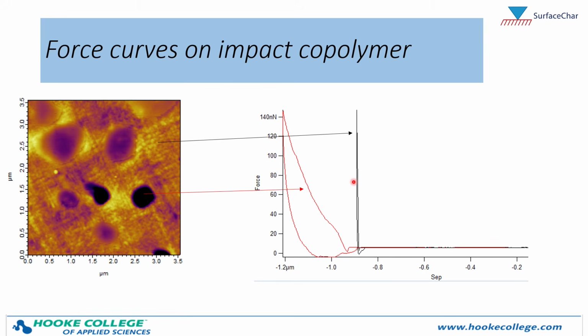So notice we have a pretty big adhesion gap here in the red curve on the rubber versus a much smaller adhesion on the thermoplastic, which makes a lot of sense. And finally, I'd like to point out the hysteresis between the approach and retract on the rubber, much bigger gap here than on the thermoplastic, and this corresponds to viscoelasticity. So the rubber domains are clearly more viscoelastic than the thermoplastic. Again, not a surprise here.